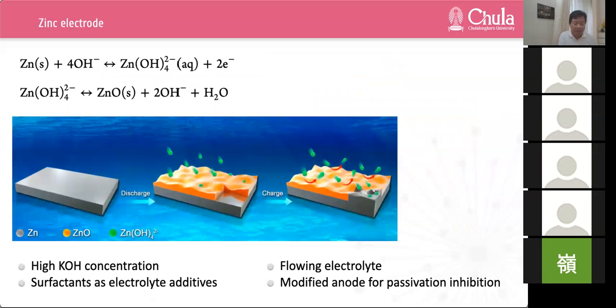While zinc air battery usually uses zinc metal as an anode active material, we expect oxidation of zinc to occur during discharge. Although the zinc corrosion rate is slower than that of aluminum in an alkali solution, this corrosion process generates hydrogen gas through hydrogen evolution reaction. We call it HER. It is more reasonable to consider the electrochemical behavior of zinc metal in the alkali electrolyte, not just zinc metal in the gas phase. So the zinc electrodes suffer from critical problems such as passivation, dendrite growth, and hydrogen evolution reaction, or HER, during operation of the battery, limiting the practical application by weakening the discharge performance and reducing the shelf life and cycling life of the rechargeable zinc air battery.